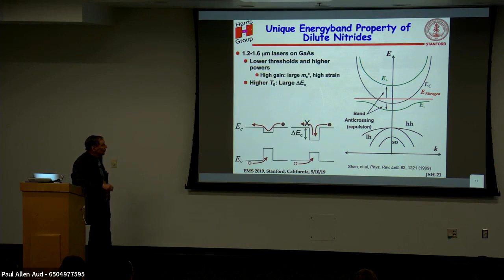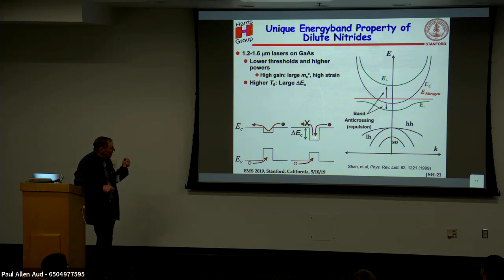So that means in this region, you have a smaller band gap material. And it turns out that it's rather fortuitous that, compared to indium phosphide, where the conduction band offset is smaller than in the valence band, and because of the small effective mass, that's the main reason you can't get really high pumping power out of indium phosphide-based lasers. Otherwise, they'd be used as all the pump lasers for neodymium and all the solid-state lasers. But we can put just enough indium in with gallium arsenide, and so the effective well that you get is much deeper, and so either from temperature or pumping it hard, you can keep the carriers much better in the conduction band quantum well than you can with indium phosphide.